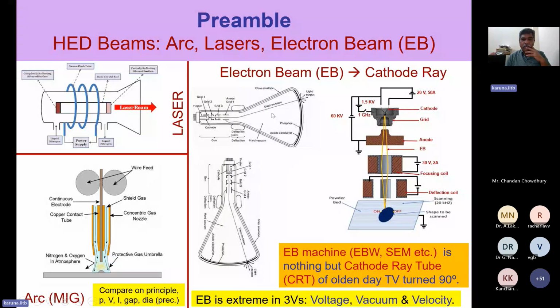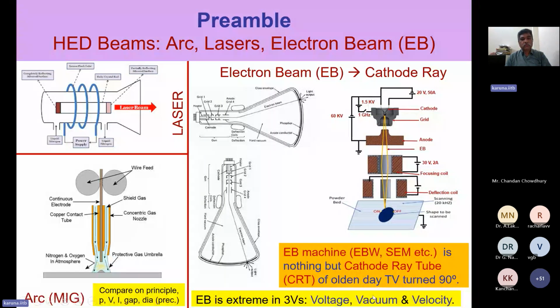So the electron beam gives us three challenges which start with the first letter V. One challenge is vacuum. The entire thing has to be in vacuum. Another challenge is voltage. 60 kV is the minimum. Up to 60 kV, you don't get any other radiations. The moment you exceed 60 kV, X-radiation and other radiations come. So you need to make the wall thick. You have to put lead-lined protections and all. So that is related to the voltage.